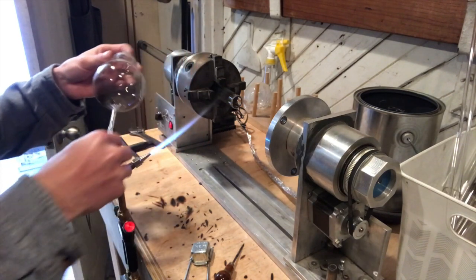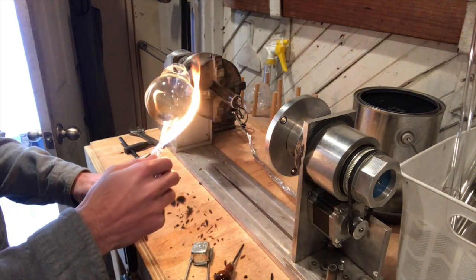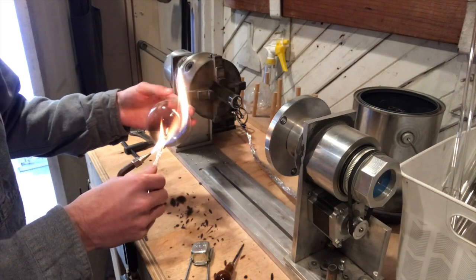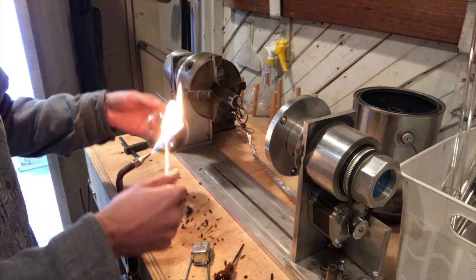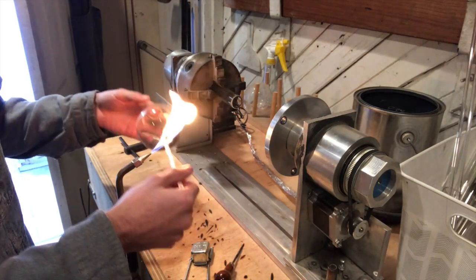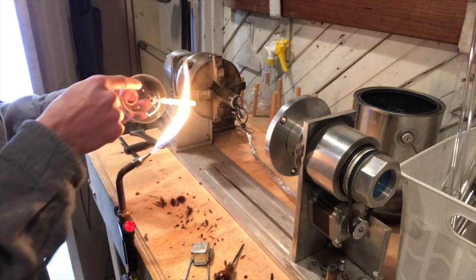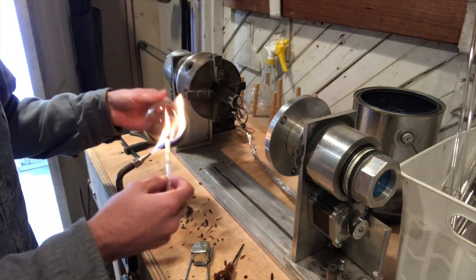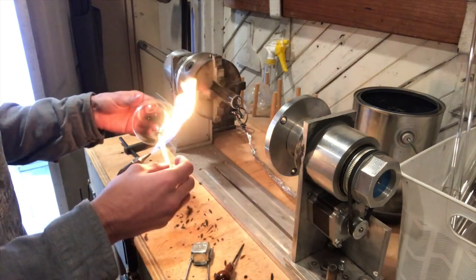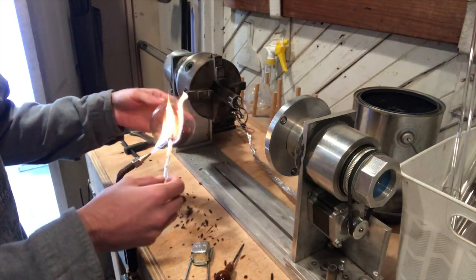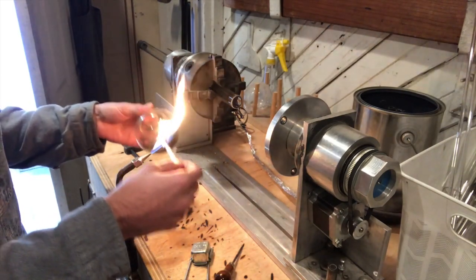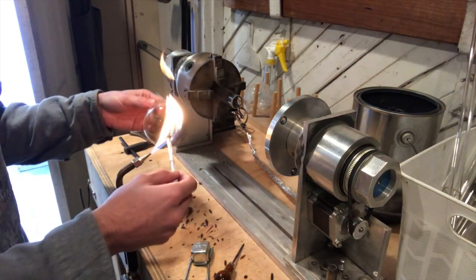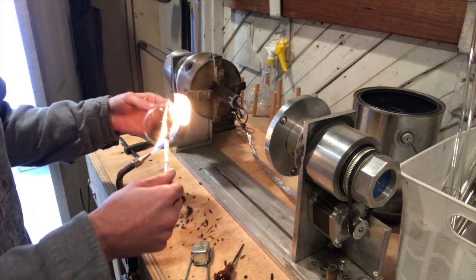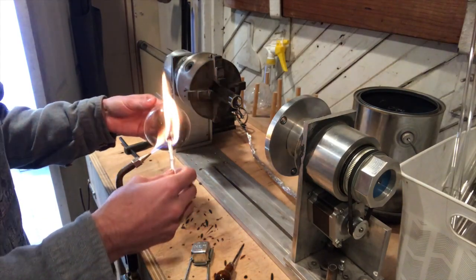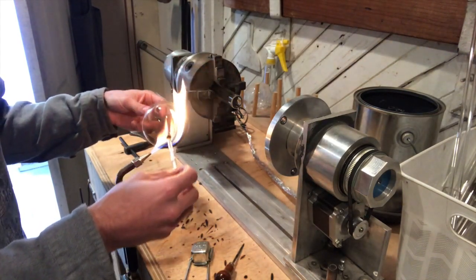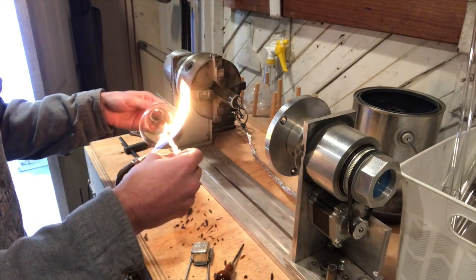Okay, there we go. Now let's anneal it. As I've stated before, if we fail to anneal, especially something such as this, which is relatively thin, or this part of the lamp process, then we will get a cracking around the top of the envelope, either if we apply the slightest of heat afterwards after we let it cool down, because I must note that in the lab right now it's about 40 degrees Fahrenheit, so of course that temperature difference after the glass is worked with heat, that significantly could cause damage in the form of cracking, so we want to anneal this quite well.